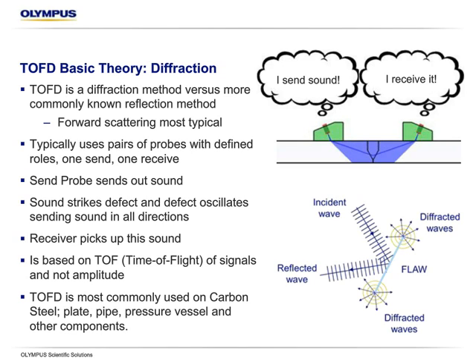So the main difference that we really see with time of flight is, unlike pulse echo, phased array, shear wave, we're not really all that concerned about the amplitude response of the signals. As long as we can hit that with enough energy, make the flaw vibrate, and get a little bit of sound back, we're going to use the time of flight to make our length, height, and other indications as to whether or not that flaw is okay to remain inside whatever we're inspecting.